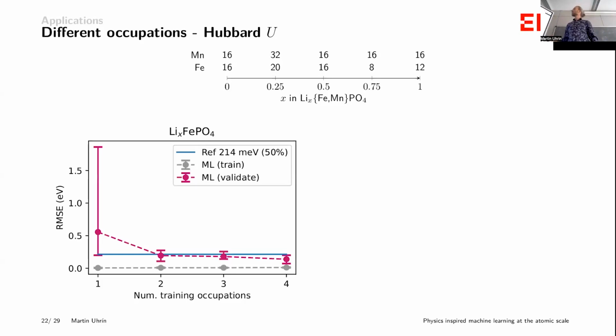So in this LiFePO4, when I show it 1, it's already at a fairly good number, 0.5. By the time I show it 2 out of the 5 of these, it's already doing very, very well. Almost as well as if I show it 4 and I'm only predicting the last 1. So that tells me, okay, great. And it's not obvious that this should happen, because if you imagine, depending on how much lithium there is, the oxidation state of these elements is going to change. So the electronic structure is really quite different. In reality, it's already enough to show it 2, and it can extrapolate successfully to the rest.